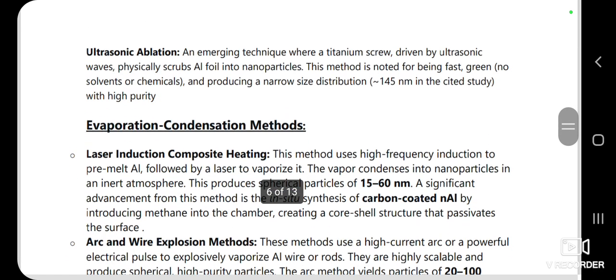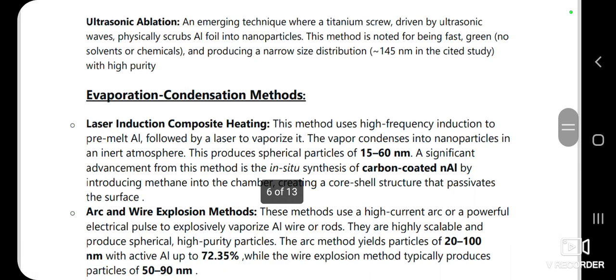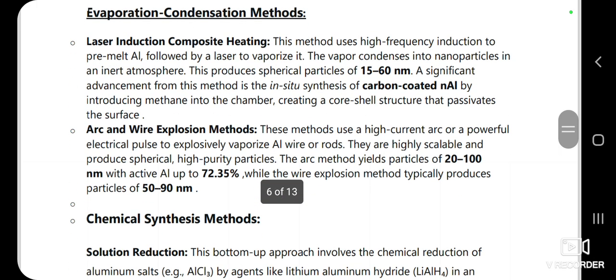And the next method is ultrasonic ablation. It's an emerging technique where a titanium screw driven by ultrasonic waves physically scrubs aluminium foil into nanoparticles. This method is noted for being fast, green, and producing a narrow size distribution with high purity. The next method is about evaporation condensation methods. The first is laser induction composite heating. This method uses high frequency induction to pre-melt aluminium followed by a laser to vaporize it.